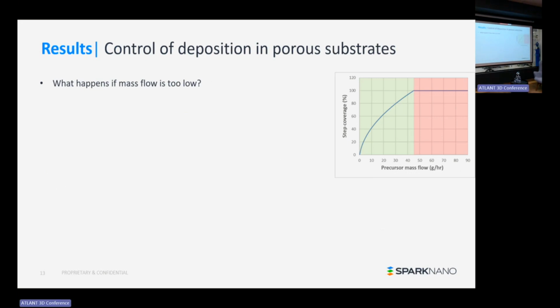So why is this important? Well, what happens if mass flow is too low? Here I plotted the step coverage that you can achieve as a function of the precursor mass flow. If your precursor mass flow is too low, this means that you do not reach your desired step coverage, the coating depth is too low, and you are in what we call supply limitation. You just didn't supply enough precursor to reach the step coverage that you want. And of course, this can impact the performance of your device.